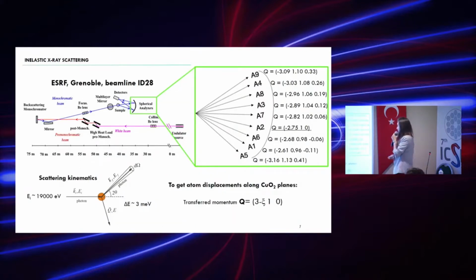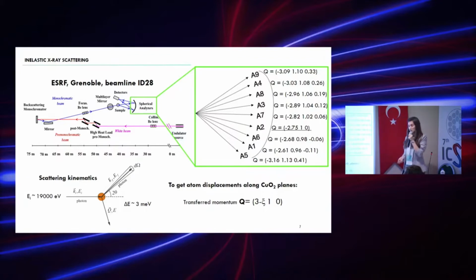To do that, we went to ESRF beamline ID28, and that's the schematic of this beamline. But what is most important for us is the resolution that this beamline can give us. It's about 3 millielectronvolts, so we can really differentiate between different phonon modes. That's quite important for us, especially if we want to compare to the older data with lower resolution. And we explored phonon dispersion along the copper-oxygen planes and copper-oxygen chains along this direction, with transferred momentum as the one mentioned here.